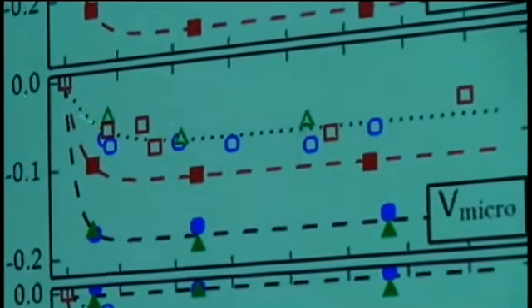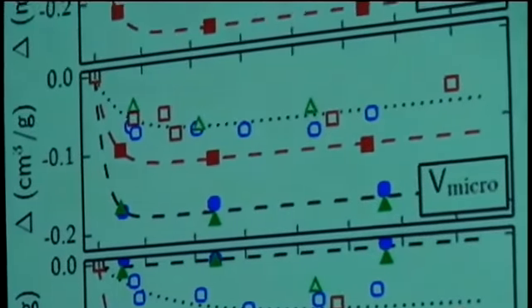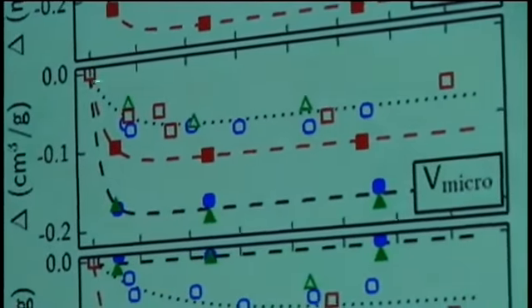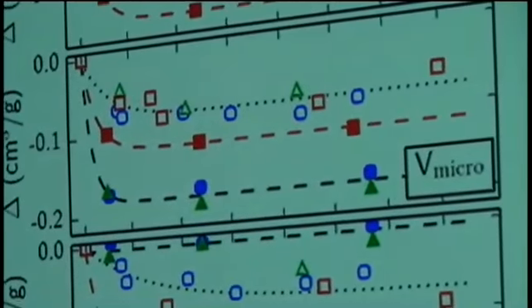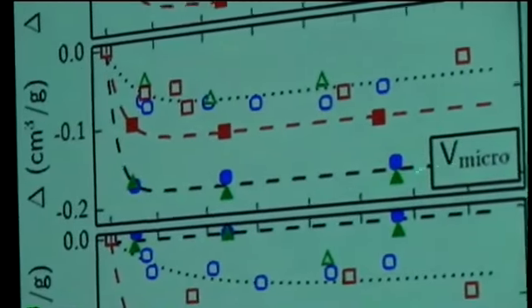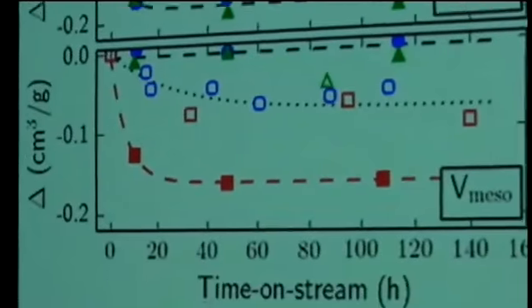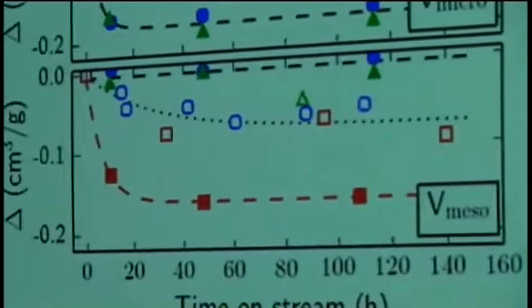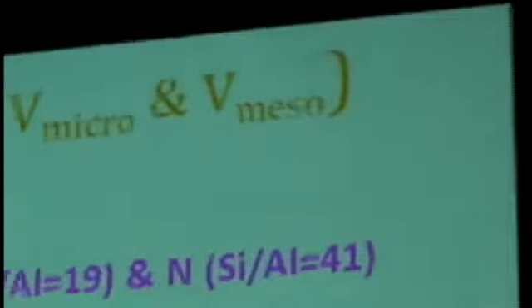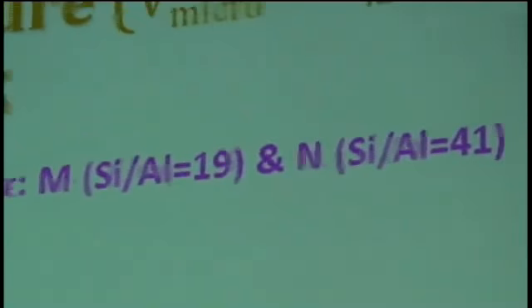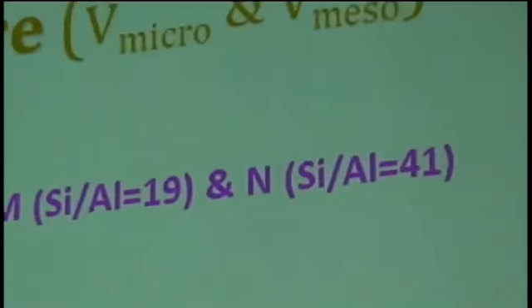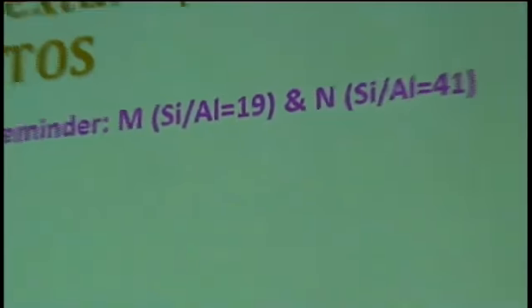I will skip the number of Lewis sites, and if you look here at the micropore volume, you see that for all the nano-sized zeolites the micropore volume decreases but doesn't go to zero, while for the micron-sized material they are all plugged by coke inside the material. So if we summarize, reminder, we are dealing with two zeolites that have different silicon to aluminum ratios, so you need to do some gymnastics when you think about the problem.